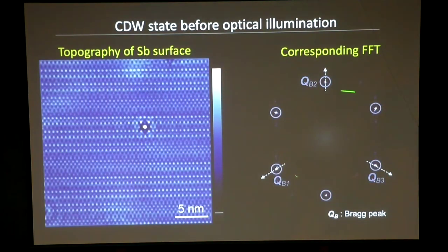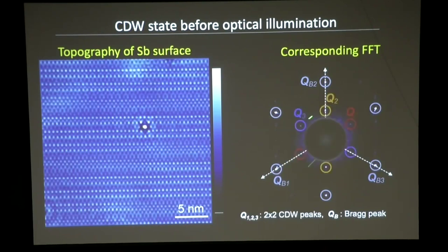So let me just march you through what we see in the Fourier transform of this compound. So this is topography. You can see the atoms in this material. You can also see one of the charge density waves. So you can see these stripes. These stripes are an additional periodicity that represent one of the CDWs. So first, let me point out the Bragg peaks. You have six of them. These are the Bragg peaks. And then inside, you have the six charge density wave peaks. And then additionally, you have quasiparticle interference. I showed you this before. This tells you about the band structure of the material.